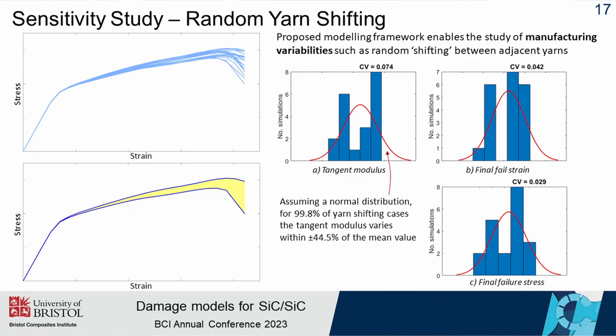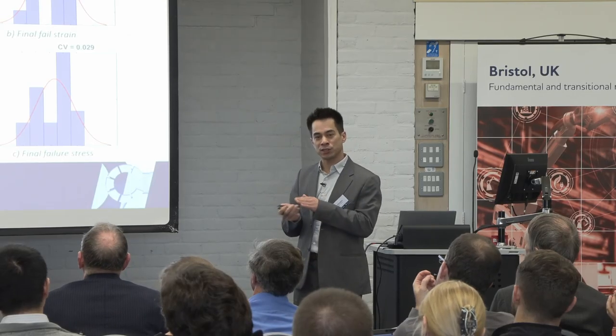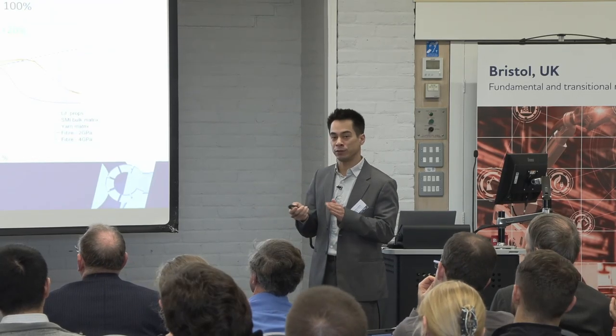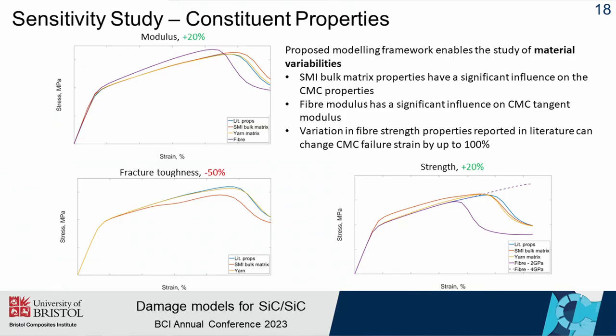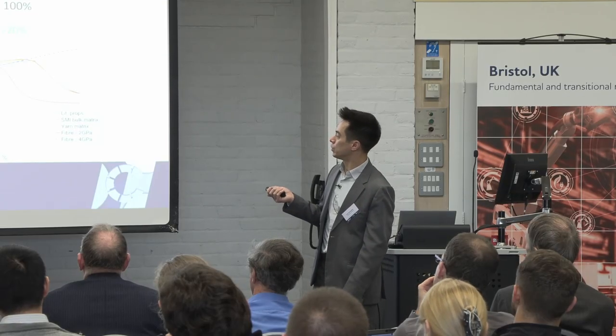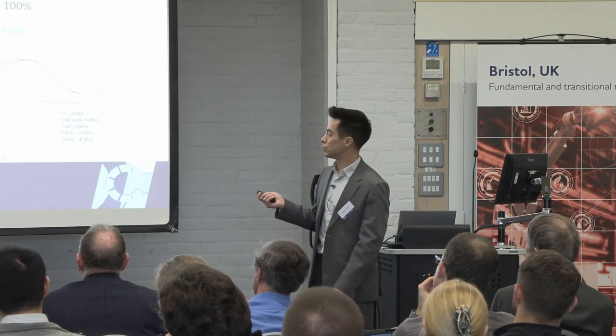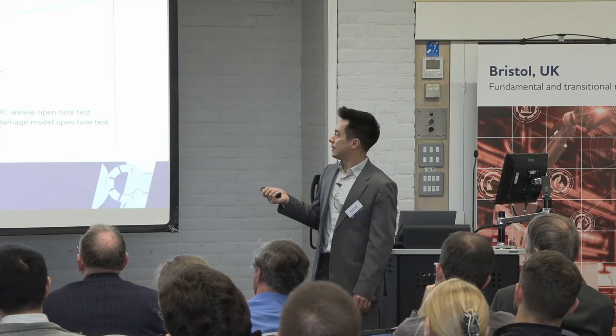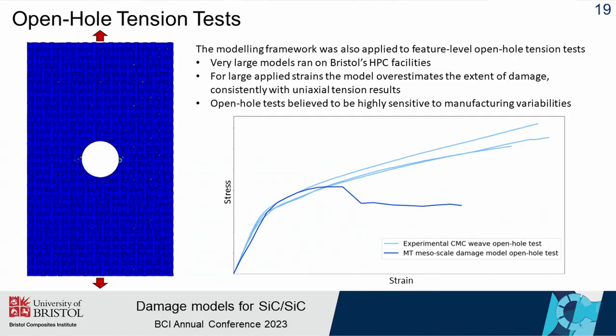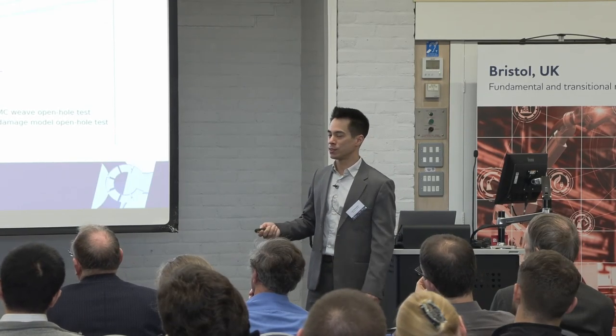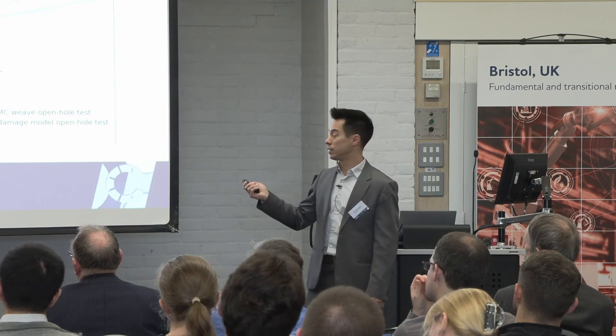a considerable variation in the properties by just that very subtle manufacturing variability, and also in the actual material properties that we adopted. By varying them from literature values to plus or minus 20 or 50%, you can evaluate the sensitivity to the results. And then one of the largest models run was a feature level model of an open-hole case, where again we get good agreement to the low strain regime and then some deviation after for the same reasons as for the uniaxial tensile tests.